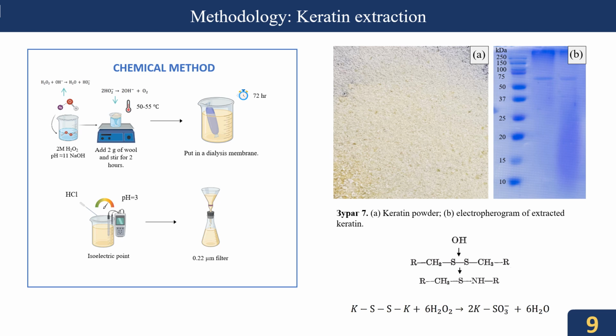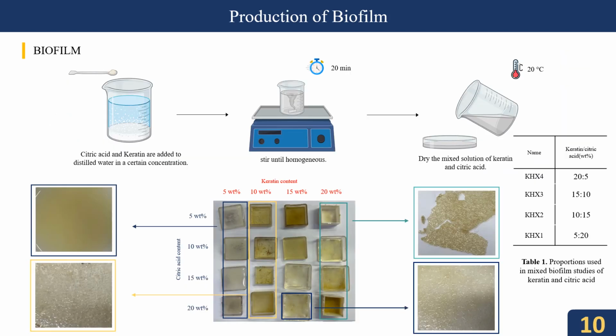So we extracted keratin using chemical methods. Of course, there are also physical and biological methods. In this method, we used hydrogen peroxide and sodium hydroxide for the reduction and extraction of keratin from sheep wool. After that, we checked the keratin molecular weight using SDS-PAGE electrophoresis. For biofilm production, we simply mixed the citric acid solution with the keratin solution. After mixing, we homogenized it at room temperature for 20 minutes, and then cast it in the appropriate wells.